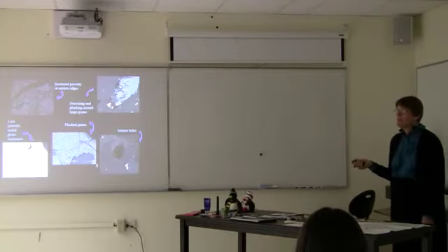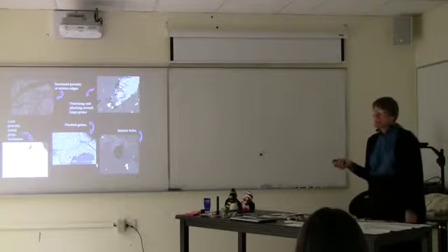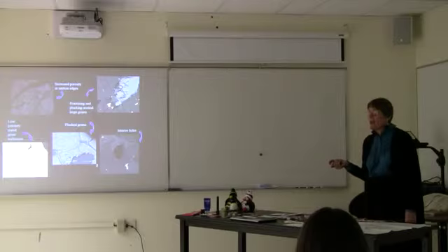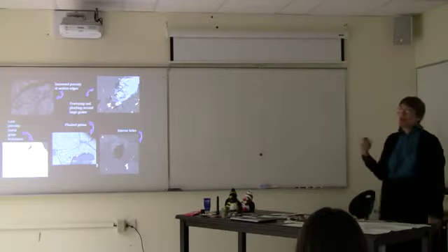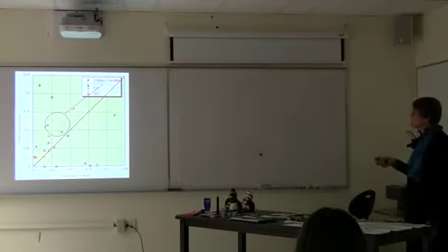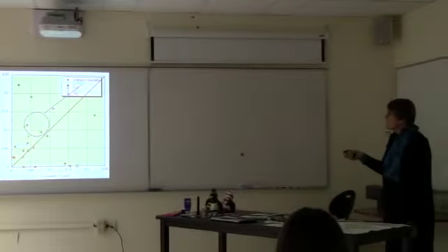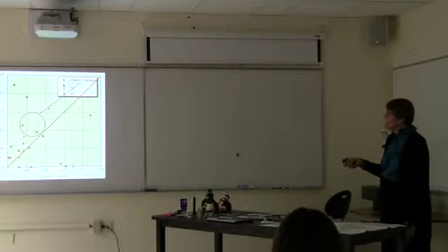So I've come to the conclusion that there's not as much damage in these thin sections for what I'm doing as people seem to think, and that I've learned to recognize what to count and what not to count, and continue then to get good agreement for the most part. We had a group we did with the Ordinary Chondrites. I did my, and you can see one of them agrees reasonably well. Two of them are fairly far off. My numbers are low compared to what they were getting with pycnometry.